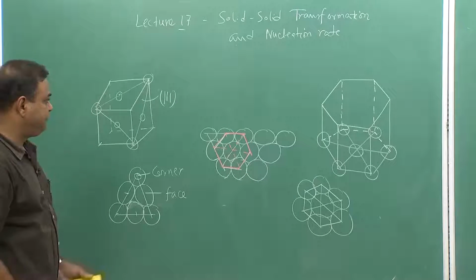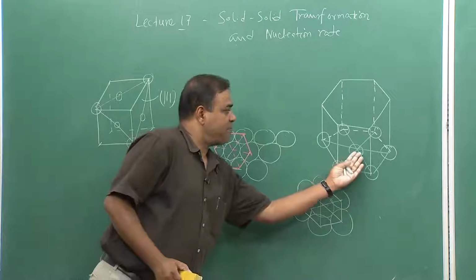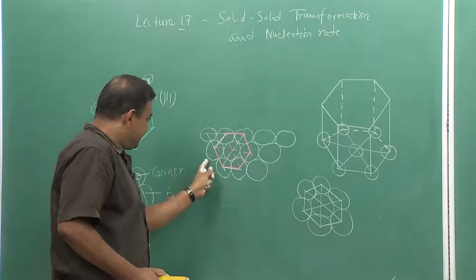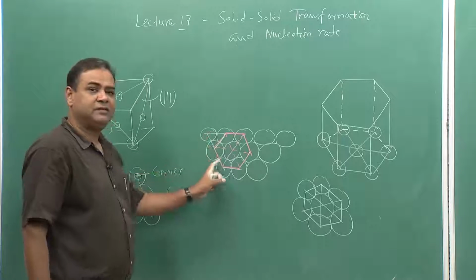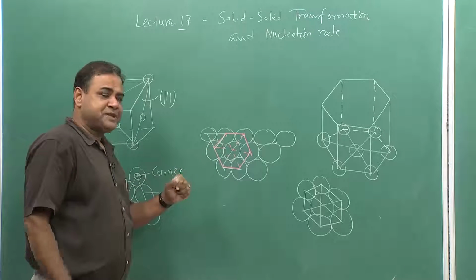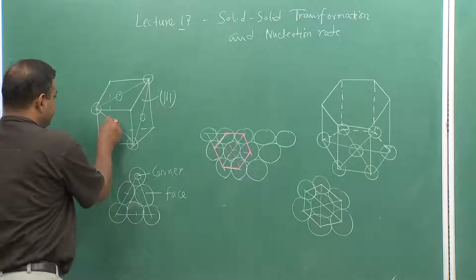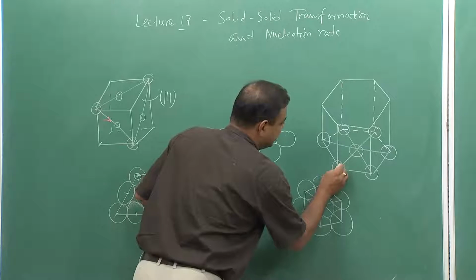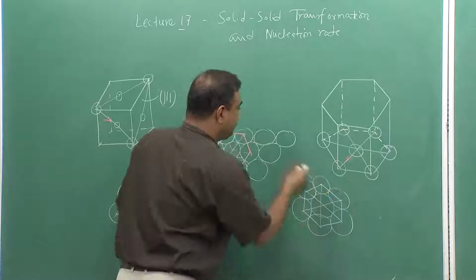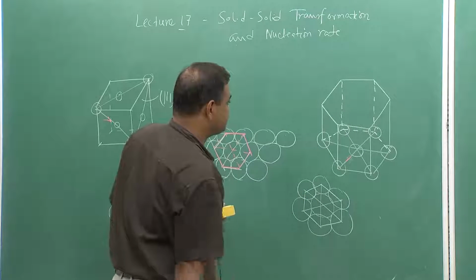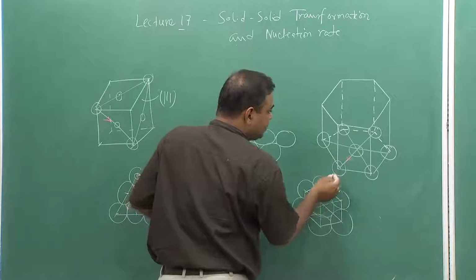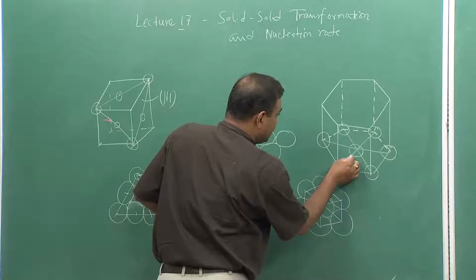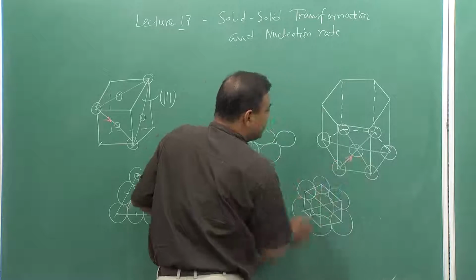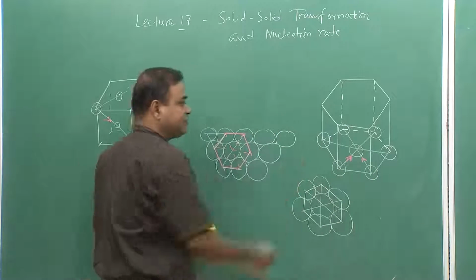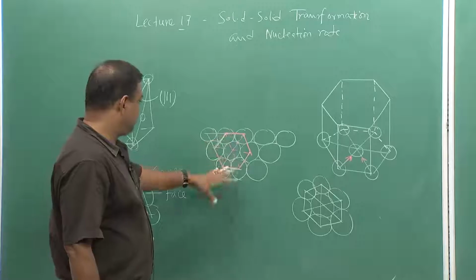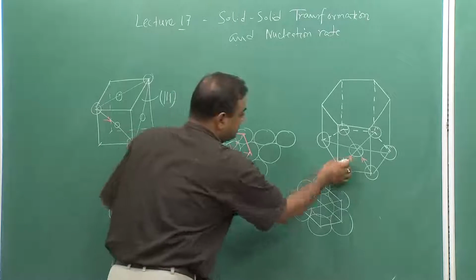So, I see that if this face is parallel to this face, then there will be exact matching of the planes, planar atoms. At the same time, if I see the direction, this direction, and in this case the direction like this, then in case of 1 1 2 bar 0, so it would be one of those kind of directions. Now we have seen that direction-wise also these directions and these directions are parallel.